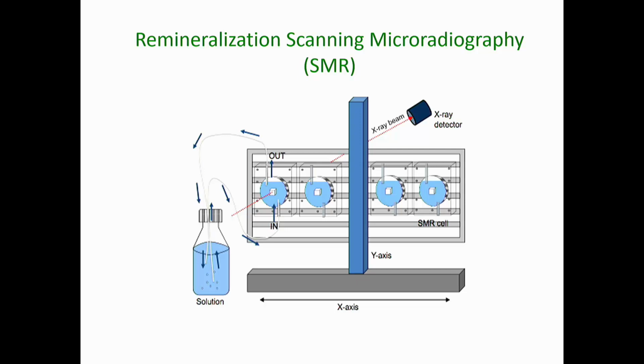We have also measured how effective the Biomin F toothpaste is in promoting remineralization. For these studies, we take a little enamel block, which I'll show you here. There is the enamel block, which sits in the center of a cell which contains about 2.5 mL of liquid, and we have passing through the enamel block an X-ray beam, and we measure the amount of the X-ray beam passing through the block, and from that we can determine how much mineral is present. So we start off by pumping through the cell an acid solution to demineralize the surface of the enamel. We do that for 24 hours. We then switch to an artificial saliva, and we apply the toothpaste to the enamel block every 12 hours.